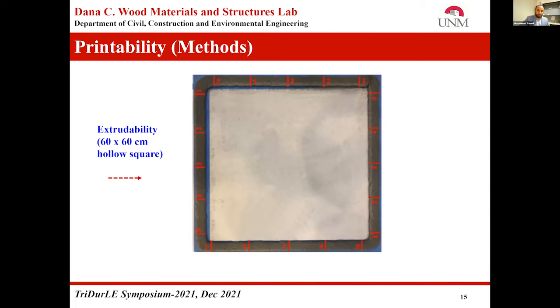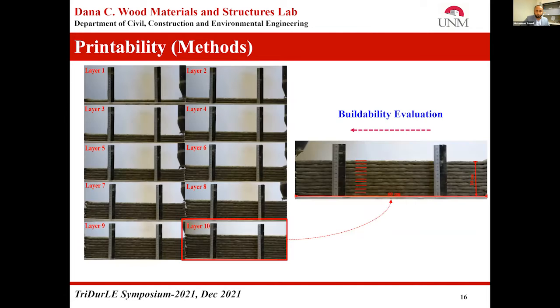The extrudability was assessed by printing a hollow square of 60 by 60 centimeters, and dimensions such as width and thickness were measured at 5 different locations of the filaments to assess the dimension conformity and consistency. For buildability, we printed a 60 by 10 centimeter wall, and the deformation of the bottom layer was monitored with respect to printing each layer on top of it. At the end, the dimension of the wall was compared with the design dimension.